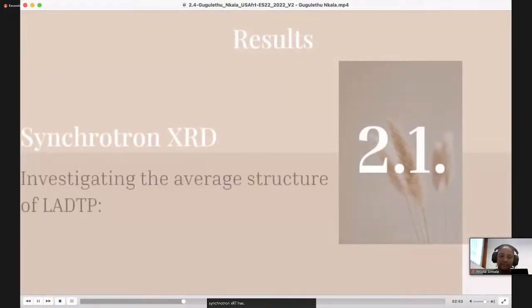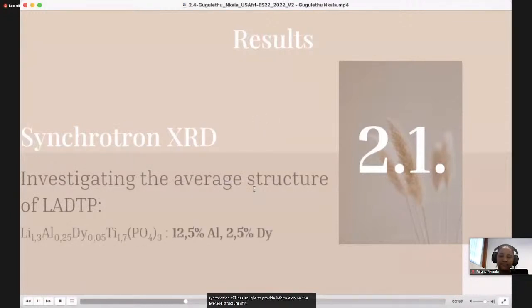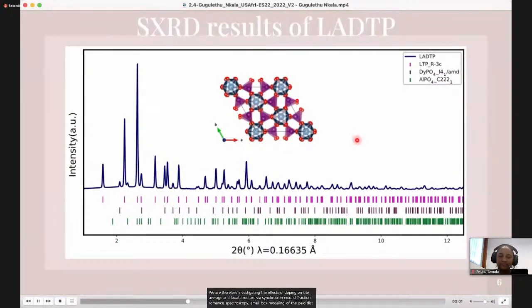Synchrotron XRD has sought to provide information on the average structure of LADTP. The highest intensity peaks in our XRD pattern have been indexed to the rhombohedral NASICON-type LTP structure. This suggests that we do have aluminium and dysprosium successfully incorporated into the structure, although this has a solubility limit shown by the formation of secondary phases such as dysprosium and aluminium phosphate. The formation of dysprosium phosphate is due to the size disparity in the ionic radius between titanium and dysprosium. Therefore, replacing titanium with the relatively larger dysprosium as well as aluminium simultaneously forces only a specific amount of these cations into the framework.